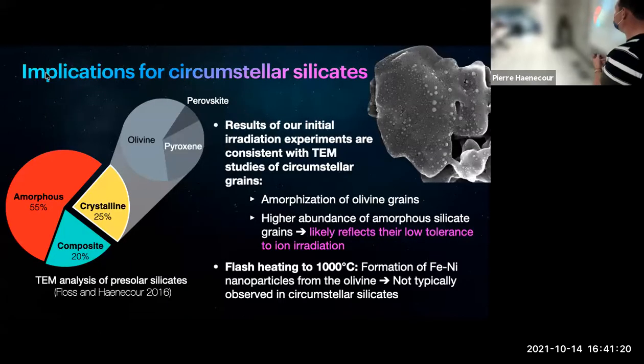In terms of implication, if we think about circumstellar silicates that are exposed to both high temperature and high energy particles, what those really initial results show, so it's really a preliminary experiment, is that our irradiation experiments are consistent with what we found from TEM studies of presolar grains in the lab. So when we look at those presolar grains in the lab, they're consistent with both.